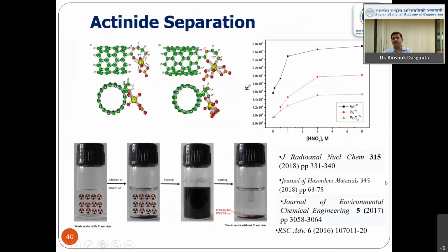Similarly, functionalized carbon nanotube has been utilized for the actinide separation. Here, a different ligand has been used, like AA, amidoamine. In this bottle, if you see, it contains uranium and americium, and then a multi-wall carbon nanotube functionalized with this amidoamine. They were added and shaken, and once you stop, all the ions of uranium and americium got absorbed onto this, and you get that ion-free water. So like this, it has been used to understand how they behave for the americium, plutonium, and all these ions, and how the kinetics of adsorption vary with the functionalized carbon nanotube.